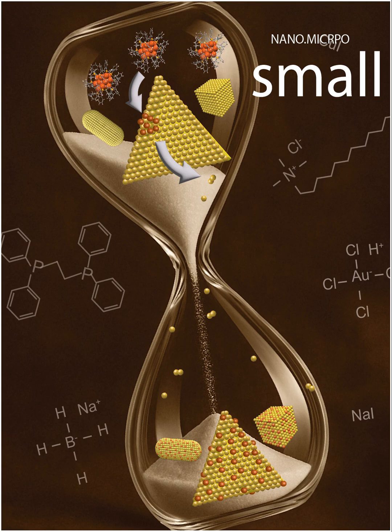Uniform alloy, shape preserved. What about the actual crystal structure? Did putting copper into the gold lattice change how the atoms are arranged? Good point. They looked at that using powder X-ray diffraction, or PXRD. This technique looks at how X-rays bounce off the atomic layers inside the crystal. They saw a pattern characteristic of what's called a face-centered cubic, or FCC, structure, which is what both pure gold and pure copper have. But importantly, they saw a slight shift in the position of the pattern's peaks.